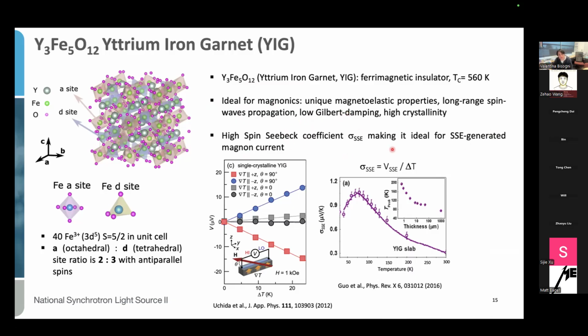And another factor that is pretty relevant, that makes this insulator stand out compared to other materials, is a very high Spin Seebeck coefficient. And this has been measured, in particular, at low temperature. As you can see here, the Spin Seebeck coefficient of Yttrium Iron Garnet has a strong temperature dependence, which is peaking around 80 Kelvin, which corresponds also to the maximum of the thermal conductivity. So which means basically that when the phonons have a very long lifetime, the magnon transport has its best efficiency here.